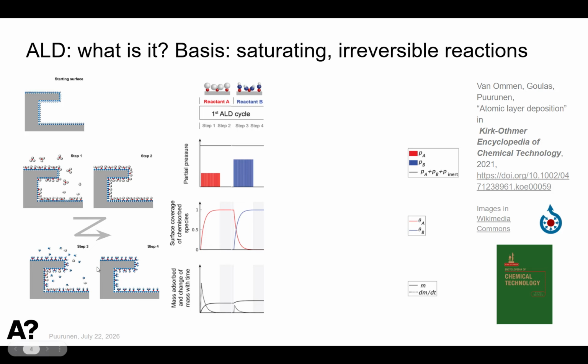example of ALD. So reactant B comes in, it reacts with the surface that was left behind by reactant A, again leaving these chemisorbed species on the surface, and in the case of TMA water, creating gaseous byproducts. In that process these would be methane, in other processes they are something else. And then again the surface gets saturated with the adsorbed species.